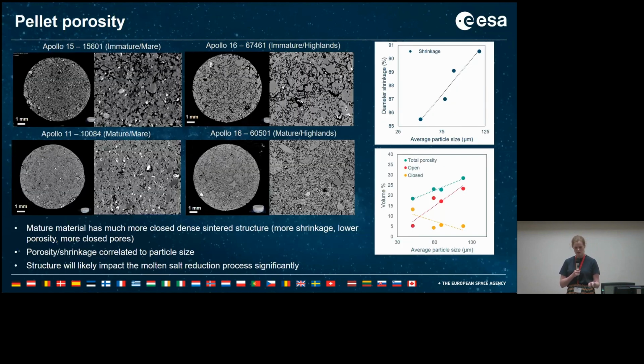And just quickly to show you some of the difference in the structure. So we see quite big, large differences between the materials. The mature material has a much more closed, dense structure, more shrinkage, lower porosity, and more closed pores, which is unsurprising given the difference in the average particle size. And the porosity and shrinkage both correlated to particle size, and the structure for this project will likely impact the molten salt processing quite significantly.